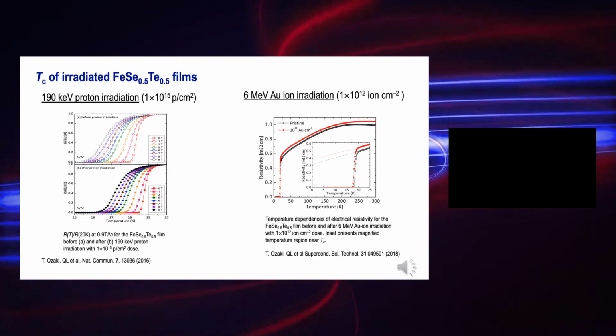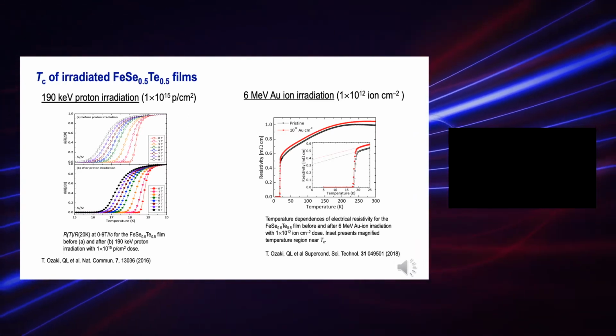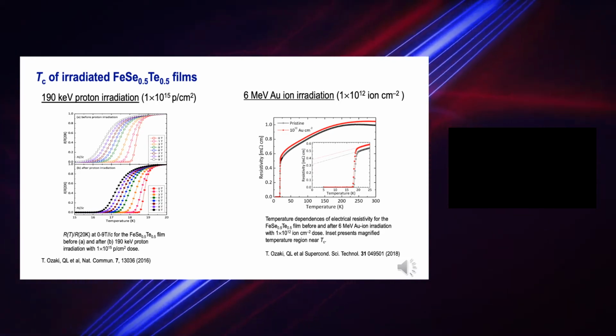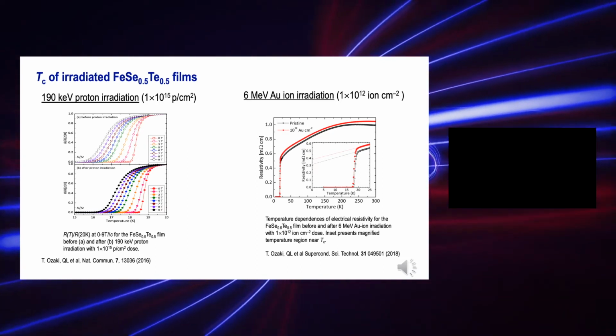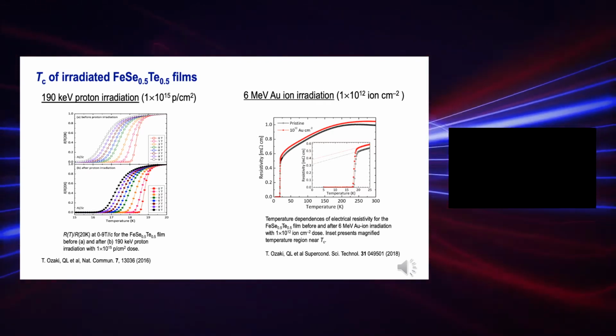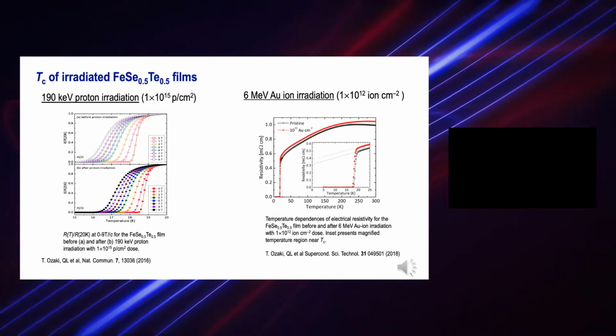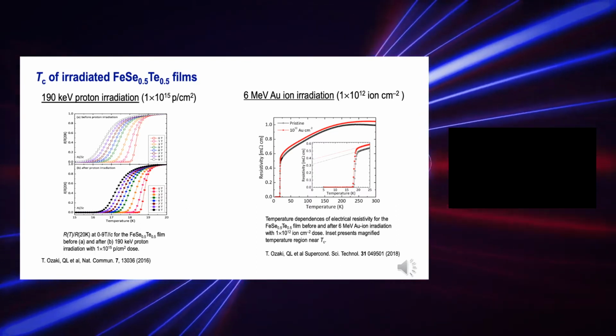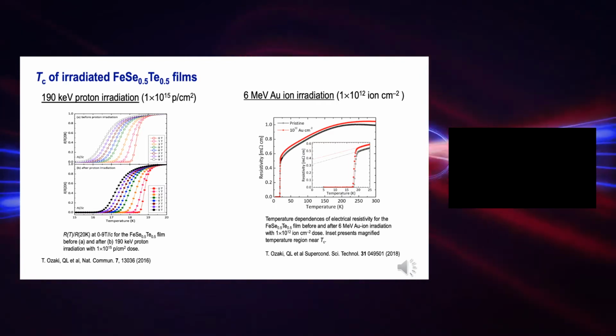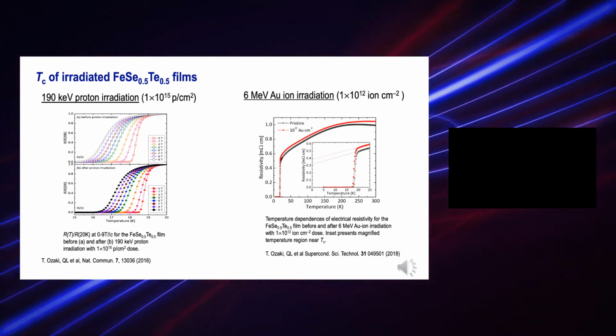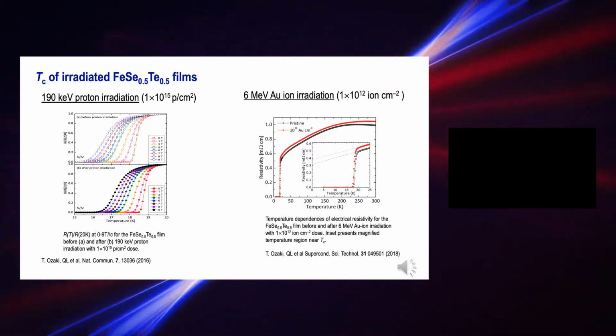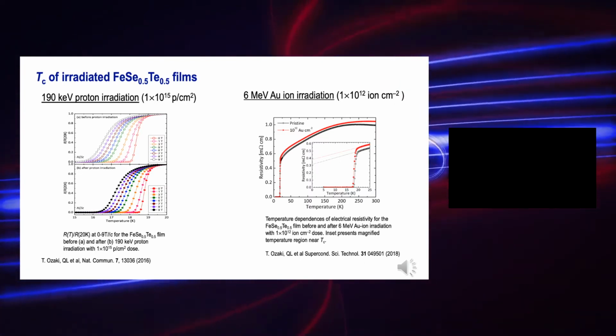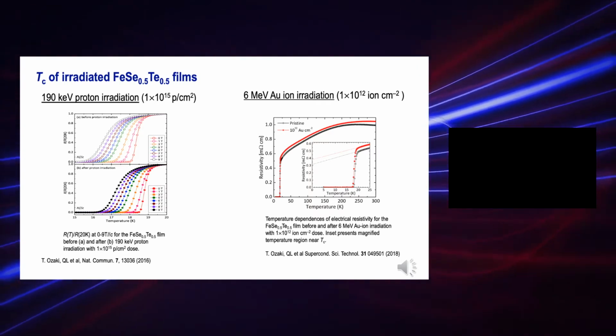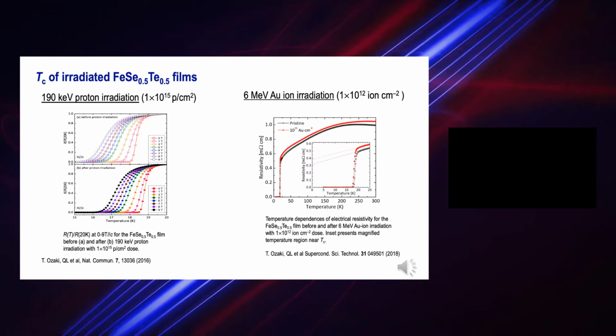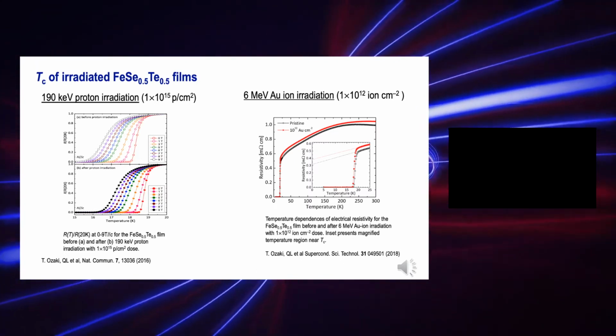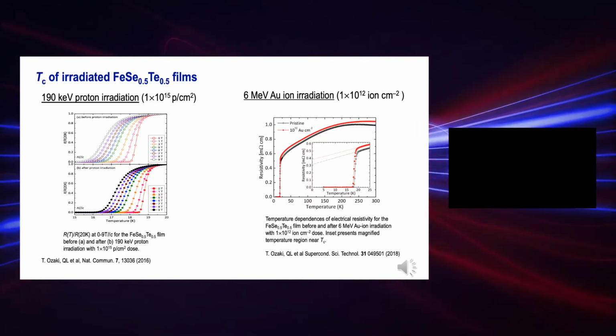So here we show you the result of irradiation on the TC of the iron chalcogenide films. For the low energy proton irradiations, we generally found that TC can be enhanced. For instance, before radiations, we have a TC of about 18.5 Kelvin at the middle point, but after radiations, we can get the zero field TC close to 19 Kelvin. But for high energy gold ion radiations, very little change in TC was observed. For instance, it is shown in the inset on the right-hand side of the figure. But overall, we see a slight increase of the normal state resistivity. Suppression of TC is really minimal.